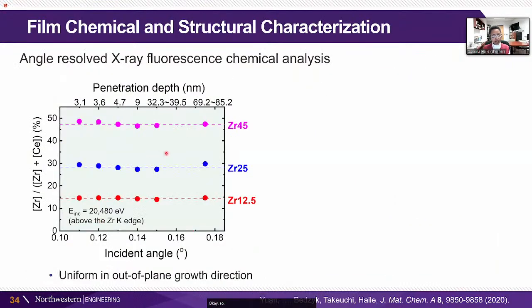Okay, so one thing that we want to make sure, because we're looking at the surface, is that there's no composition gradient between the bottom to the top of the film with respect to the zirconium concentration. And this is the top part of the film. This is the bottom part of the film. We're doing X-ray fluorescence as a function of penetration depth by changing the incident angle again. And we can see that there's no statistically significant variation in the zirconium concentration as we go through the thickness of the film.